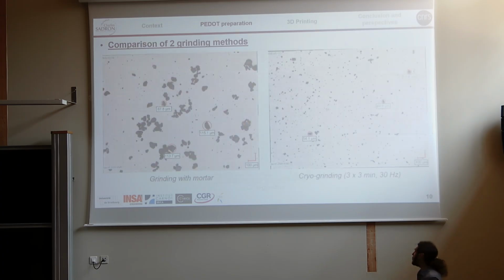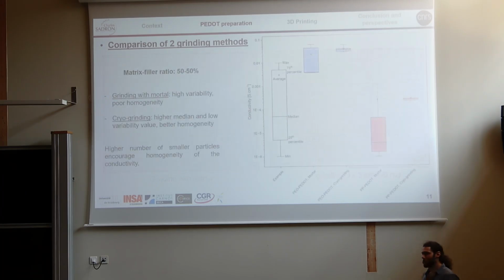The first results can be observed at the numerical microscope, where you can see that using the cryo grinder, you will have many more very small micrometer-scale particles, and the biggest particles would be just a few dozens of micrometers long, whereas with the mortar you still have much bigger particles that can go up to 100 micrometers long.